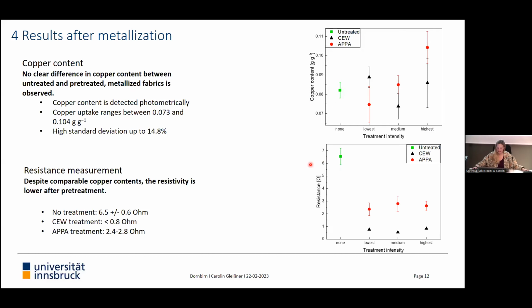From the resistance, you see a difference. The non-treated fabric is around 6.5 ohm. The plasma treated fabrics have a resistance between 2.4 to 2.8 ohm, and the complex samples have a resistance of around 0.8 ohm. Despite these similar copper contents, the resistance for the treated fabrics is lower than for the untreated fabric.